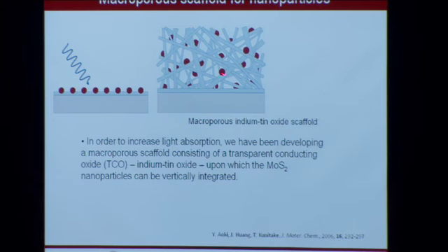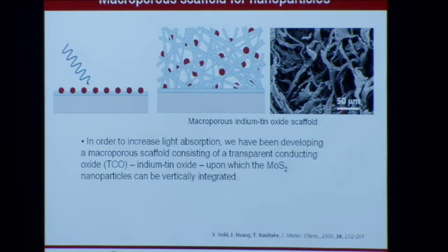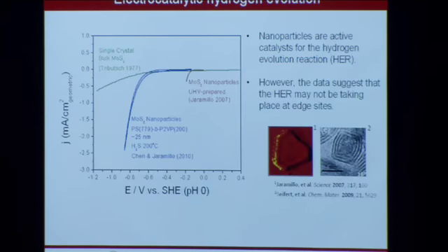And so this is conceptually what we're trying to do. We're trying to load the nanoparticles, and this is what it looks like by SEM. You can see that these are very large pores. They don't have to be small. In fact, we don't want them to be too small. Otherwise, diffusion of water in and gases out might be problematic. But nevertheless, we've taken this structure, and this is what we're going to use to measure hydrogen evolution and photoelectrochemistry on our nanoparticulate semiconductors. So in terms of hydrogen evolution, this is an experiment we did in the dark.